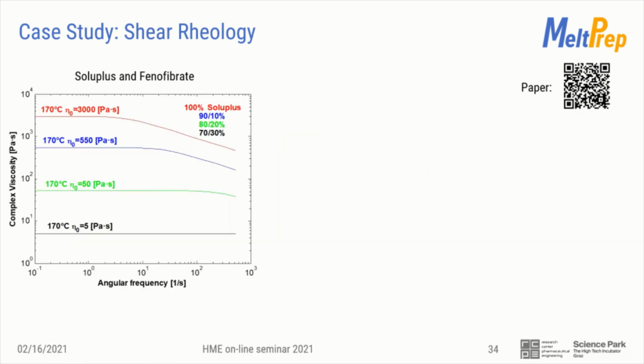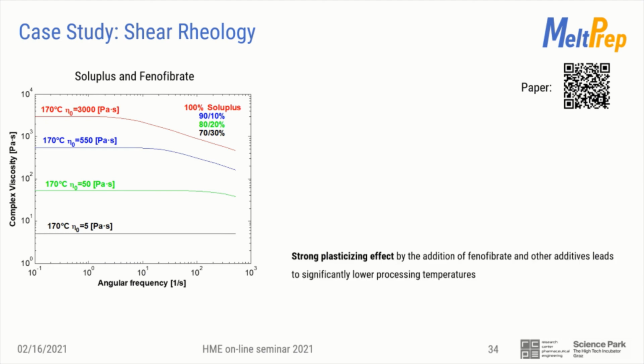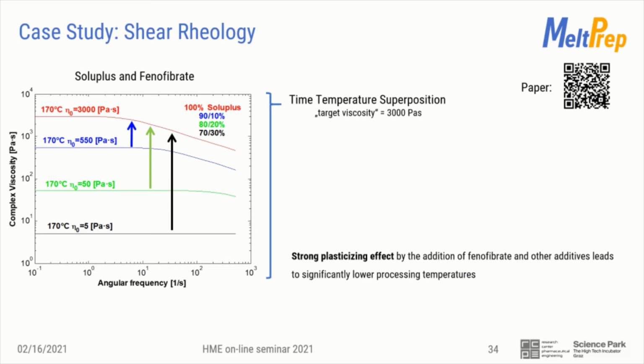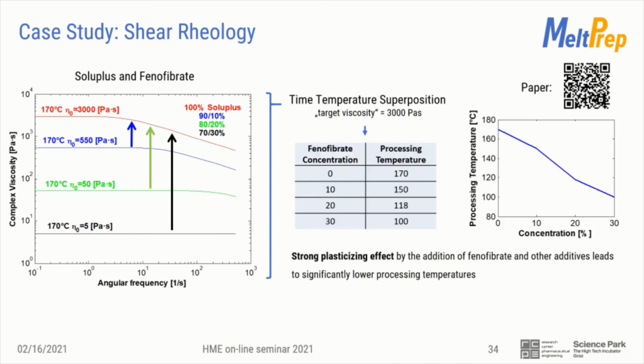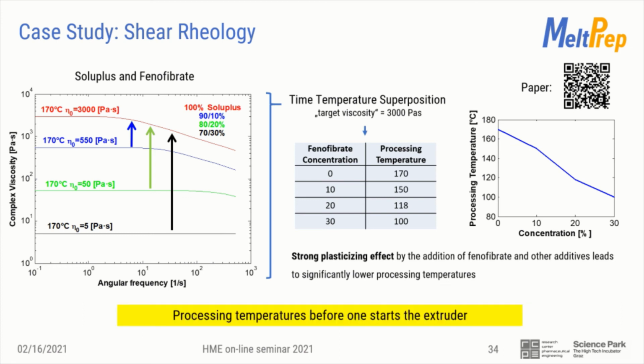How can it be applied for hot melt extrusion development? In general, the viscosity of an API-loaded system is decreasing with increasing API content. This is also known as the plasticizing effect. Adding 30% of API reduces the viscosity from 3000 Pascal seconds at 170 degrees C to only 5 Pascal seconds. The time-temperature superposition allows you to shift those curves to different temperature levels. You can predict operating temperature before starting the extruder. In this case, it predicted a temperature decrease from 170 degrees to 100 degrees C.